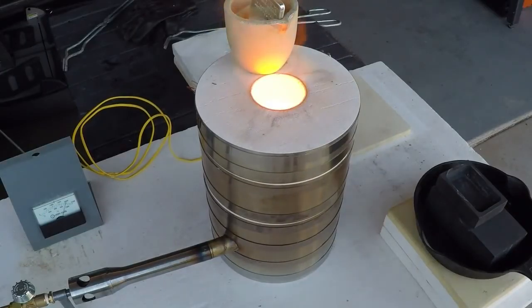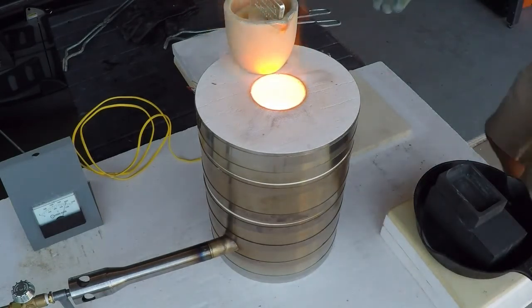Okay guys, I'm back. Kiln's running about 2,000 degrees right now, didn't take very long, about five minutes. But to keep this thing fairly short, what I've done is I like to set my crucible on top of the kiln as it's warming up and let the crucible warm up a little bit. That helps to minimize thermal shock when you put it in there. I'll grab this, we'll go ahead and charge the crucible.